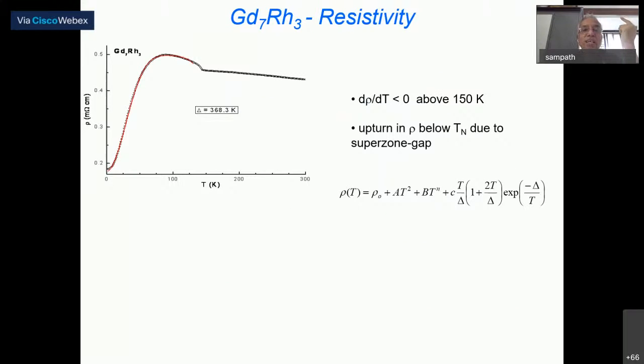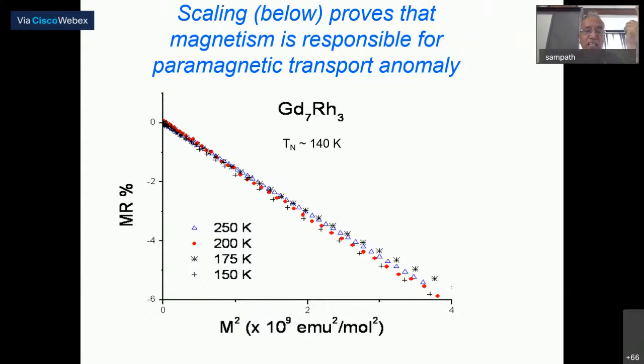And let me go to one example, Gd7Rh3, to tell you it's truly magnetic. If you plot magnetoresistance as a function of magnetization squared, you will find that in the paramagnetic state all the lines fall one over the other. There is a very beautiful scaling between magnetization and magnetoresistance in the paramagnetic state, right up to 300 Kelvin. Values are reasonably large. At 300 Kelvin, you have anything more than 0.5%. Still, for room temperature, quite a large value. This establishes that magnetism is responsible for the paramagnetic transport anomaly in gadolinium and these materials.